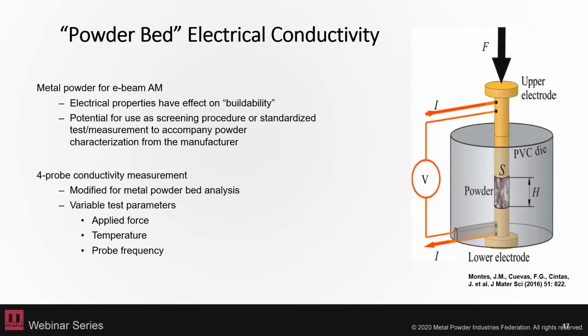Another measurement that is gaining popularity is looking at the electrical conductivity of powder beds. This is a paper published by Montes in the Journal of Materials Science. Again, apologies for my dog. For metal powder beds, their electrical conductivity is critical, especially for electron beam additive manufacturing. The electrical properties have an effect on the buildability. Like Amy mentioned, those powder beds are actually sintered together. So this could be used as a potential screening procedure, or a measurement to accompany your powder characterization data, in order to be able to characterize this powder as buildable or not buildable.